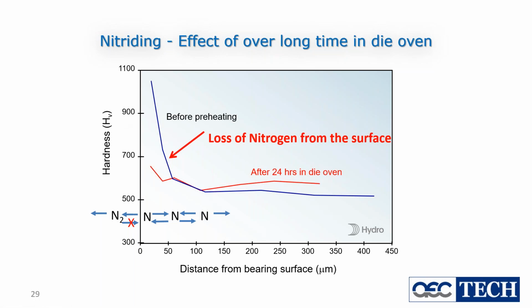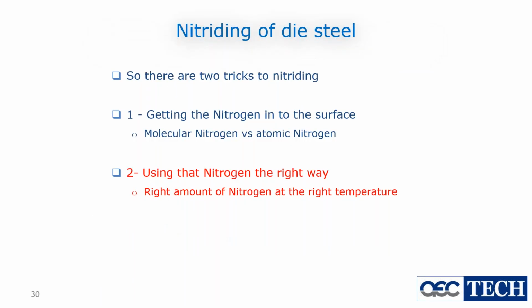We don't want to lose that valuable nitrogen we've put in there by leaving a dye in the oven for 24 hours or a week. I think the worst I've seen, I found a dye in the oven after 6 weeks. It was a very interesting conversation with my press crew as to why the dye had been in the oven for 6 weeks, but basically nobody wanted to run it because it was always a bad running dye. And I can tell you after 6 weeks in the oven, it was going to be a bad running dye. It was a self-fulfilling prophecy. But you need to respect that dye heating time.